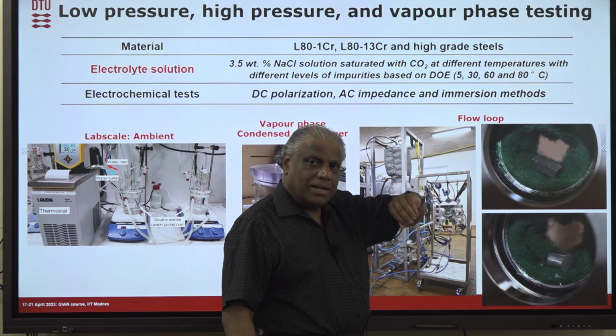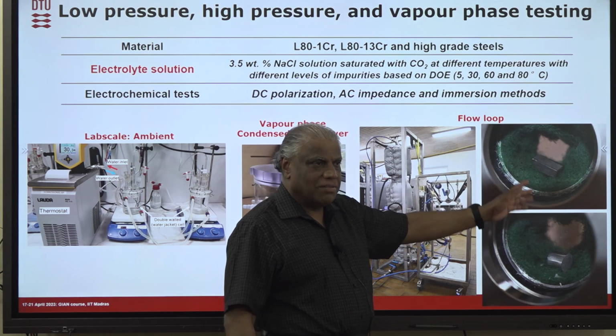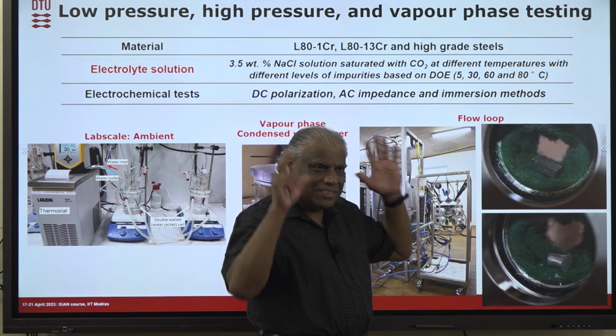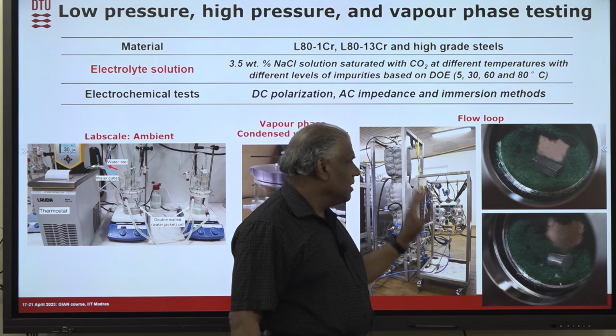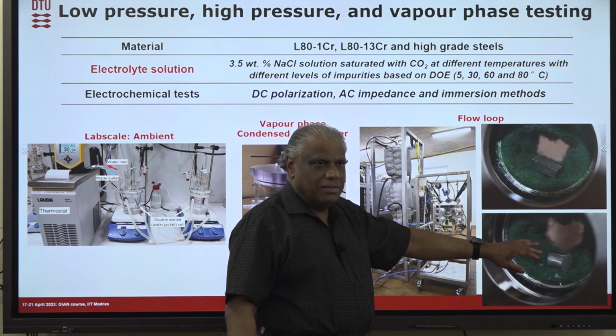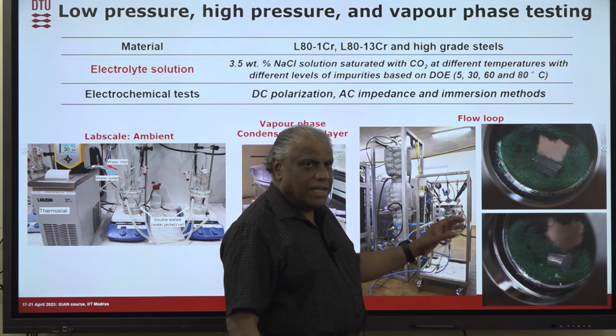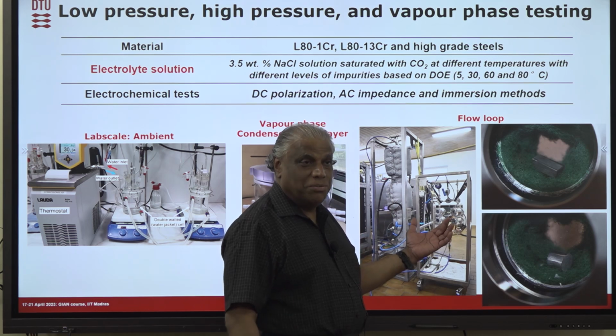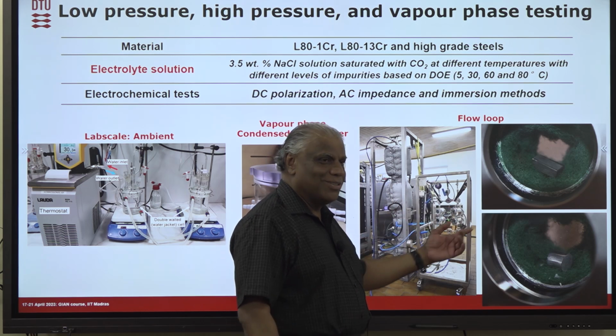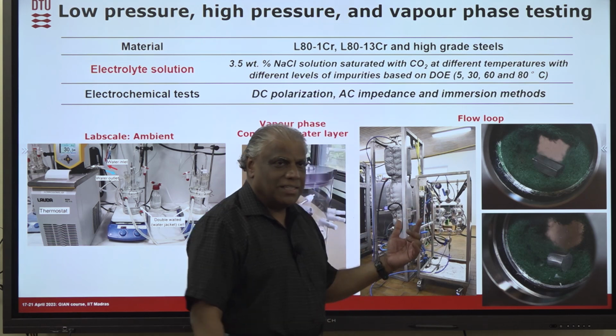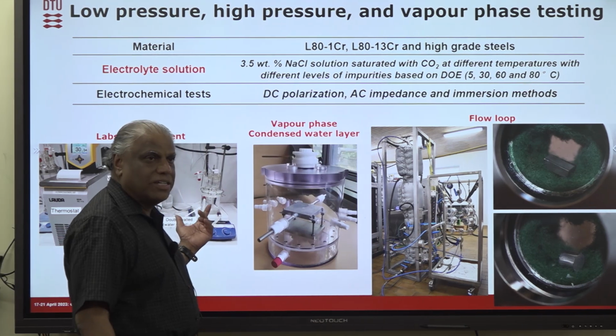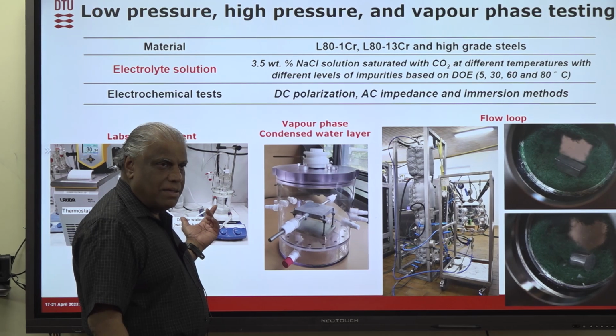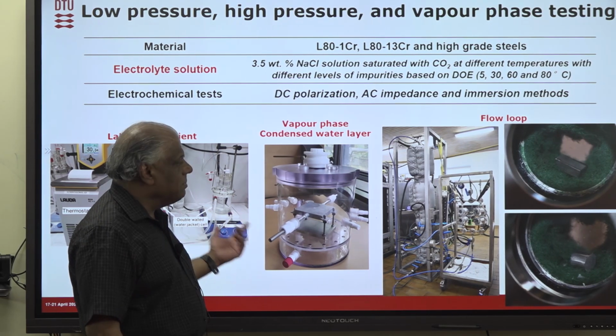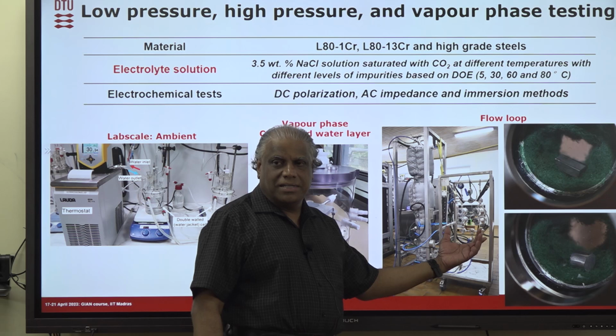Supercritical CO2, and we can contaminate that with whatever amount of water we want, whatever amount of gas we want. So exactly like what CO2 is injected, that's what we test here. The problem with the flow loop is that this testing is time consuming and it requires a lot of things. So that's the reason that we do the lab experiment, so that we can screen the parameters here, and then we know what the critical parameters are, and then we do it in the flow loop.